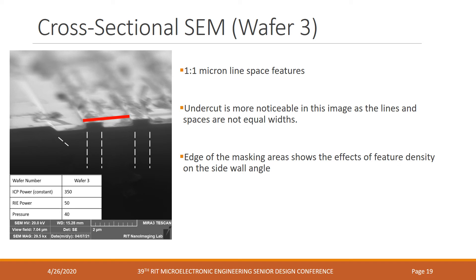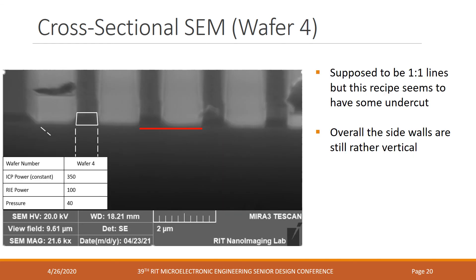The sidewall angles from wafer 3 in cross-section were much higher than the optically calculated angles, validating that pixel resolution was the limiting factor in optical measurement accuracy. It is also important to note the significance of feature density — at the edge where the field meets the active region, the electric field is much different, leading to a significantly different final etch result. More undercut was also present in the 1 micron lines of wafer 4, but the sidewall angles remained highly anisotropic and comparable to the other etches in the series.